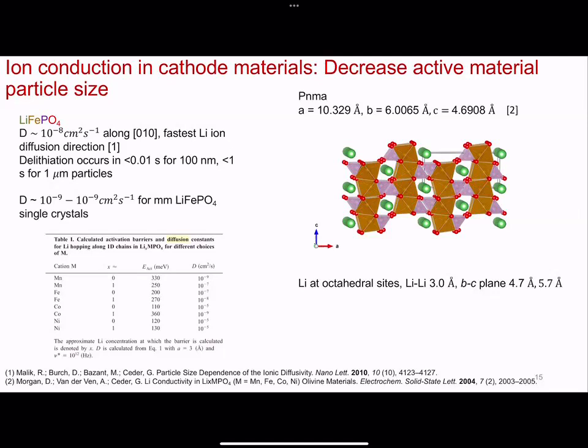And now, another really successful example is lithium iron phosphate. So this material has been studied since the 90s, early 2000s, well commercialized at this point. And if you look at the single crystal, you see that the fast ion transport direction in the single crystal is along the 010. That's the tunnel, in and out of the board. And when you look at the diffusivity, you can see that the delithiation is quite fast. It's under 0.01 second for a 100 nanometer structure, and less than a second if the particle is moving to the micrometer regime.